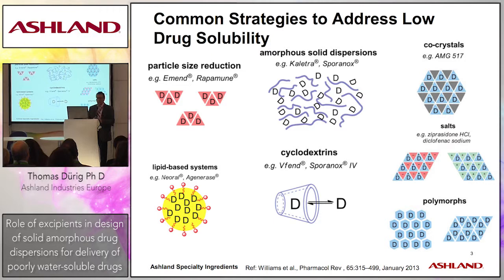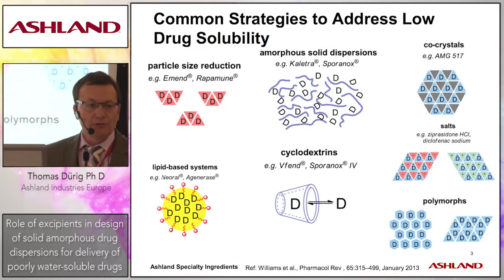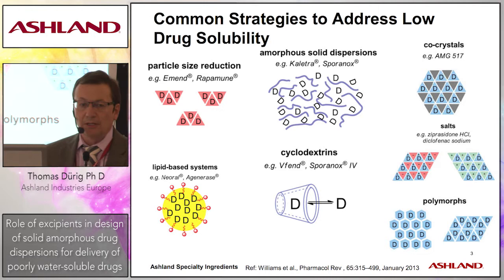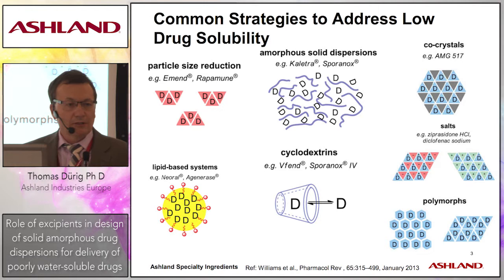Amongst all of these approaches, our topic today will mainly focus on amorphous solid dispersions, which are clearly an area of burgeoning and growing interest for commercialization in the pharmaceutical industry. An amorphous dispersion, in its simplest form, might be described as a dispersion at the molecular level — a solution at the molecular level — of an active ingredient, an API, in some sort of carrier base. Quite often, that carrier would be a water-soluble polymer.